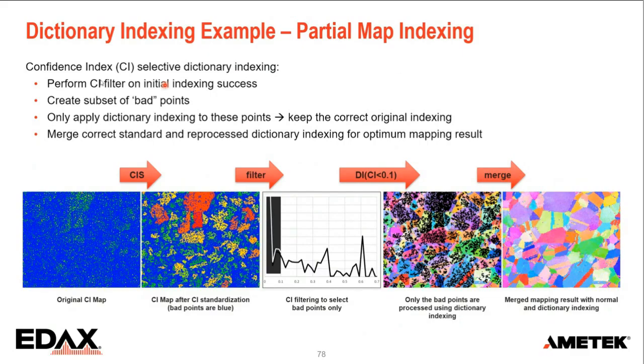So what we do, we can again use the confidence index. We look at the original map, we find the correctly indexed points that have matching orientations, and then we make a filter to only select the bad points that don't belong to grains, it's just the noise that didn't index. Then we can apply the dictionary indexing only to those points and merge that with the initial measurements. So that way you can have the best of both worlds.